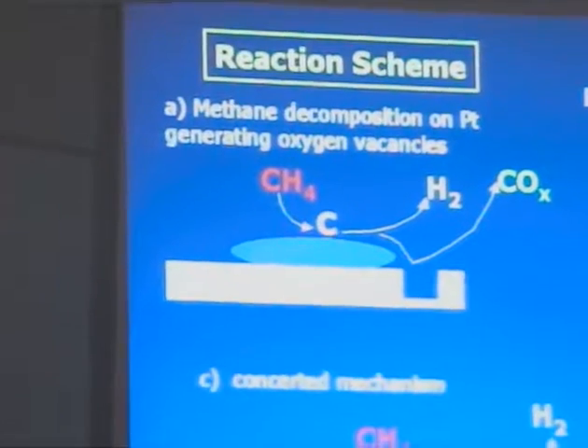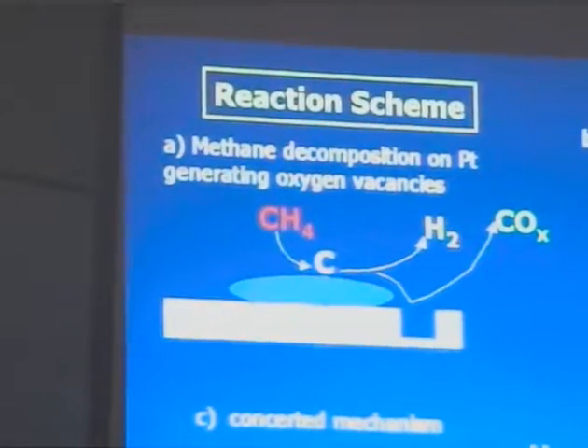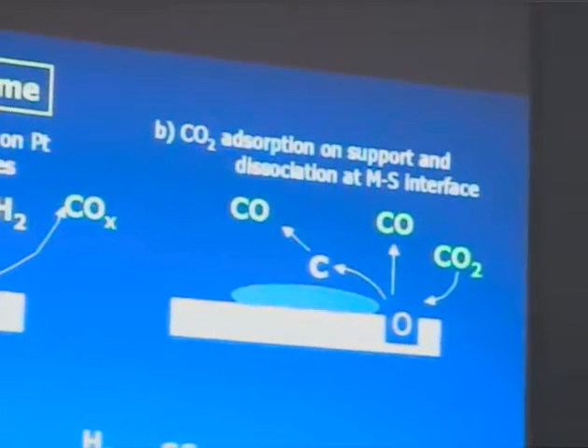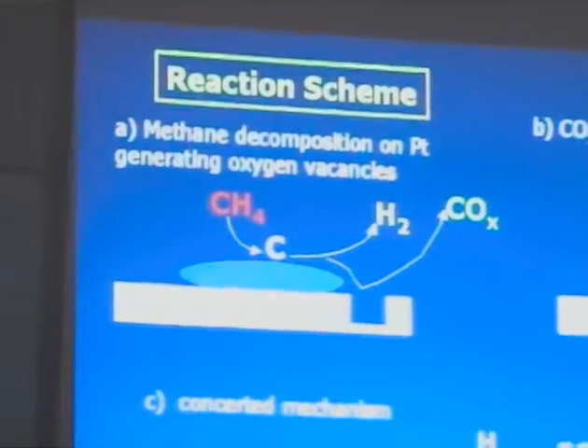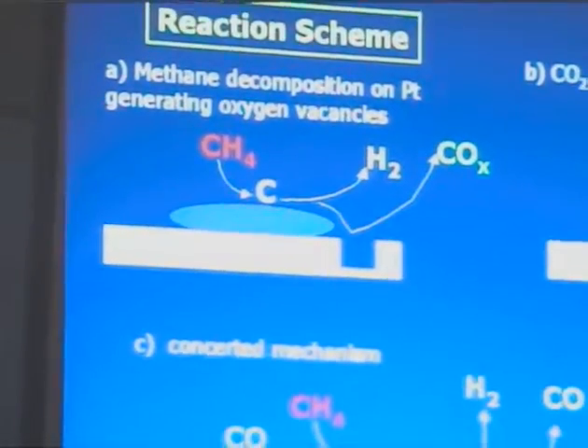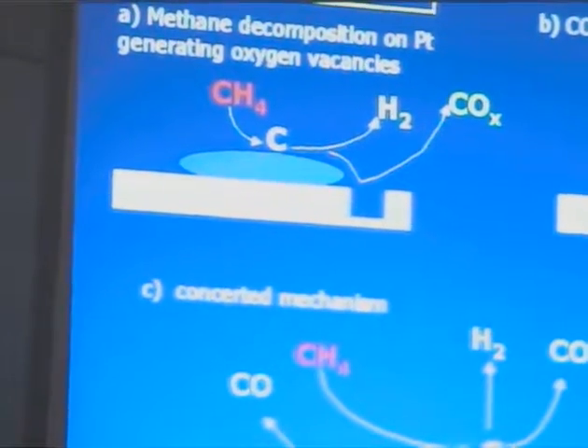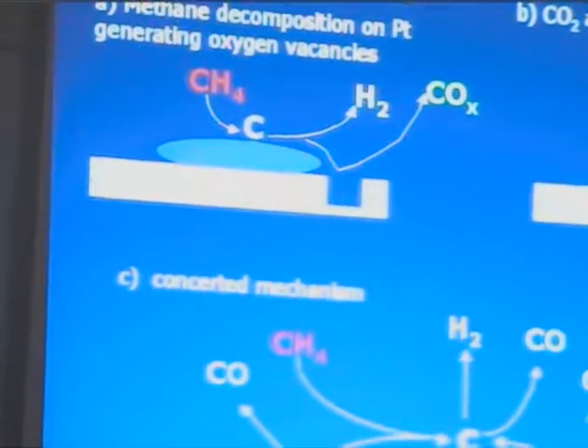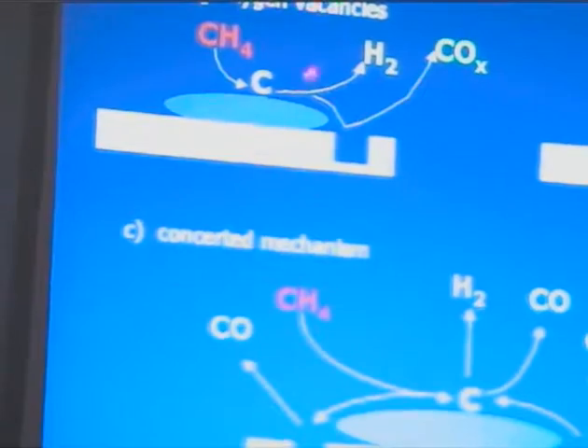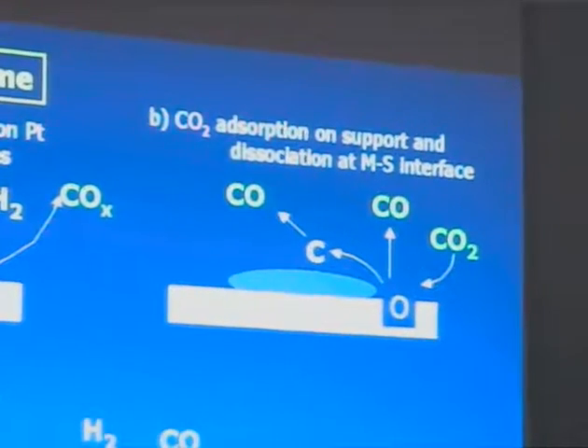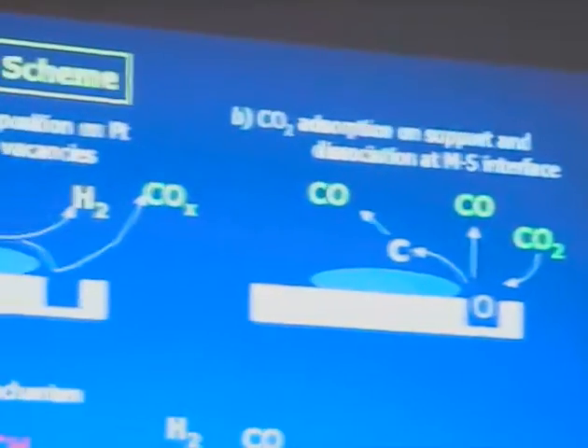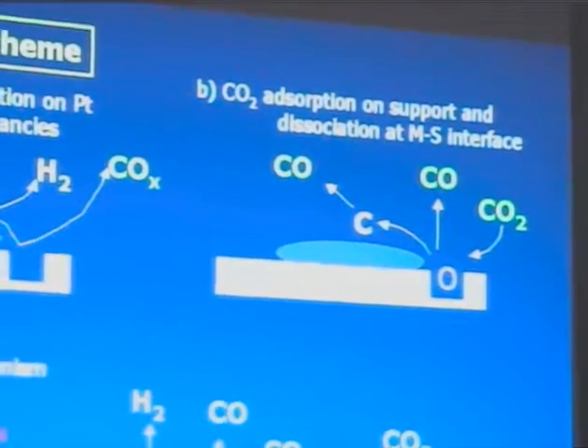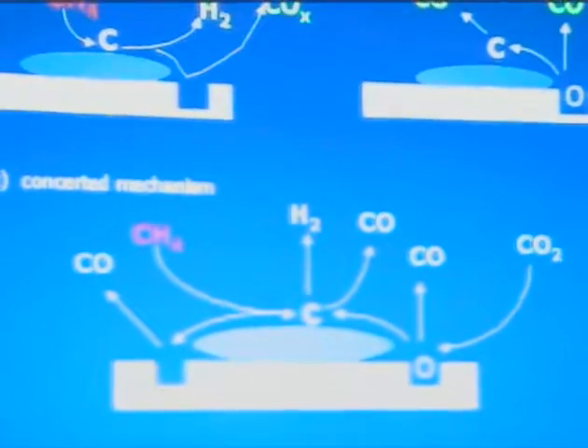This is a cartoon picture of the reaction schematic for what's happening with methane and CO2 reforming on a reducible support. The first step is that you have methane decomposition occurring on the platinum particle, and here's the cartoon of your reducible oxide. When that methane comes down on the platinum particle and decomposes, the carbon that's on the metal can interact with oxygen from the support, forming carbon monoxide and hydrogen in the gas phase. When you have CO2 adsorption on the support and dissociation, that occurs at the site of the oxygen vacancy. So CO2 adsorbs at that site. The CO2 dissociates and oxygen replenishes the vacancy in the support. And when those two happen together, you have this concerted mechanism, where you have decomposition and dissociation occurring simultaneously.